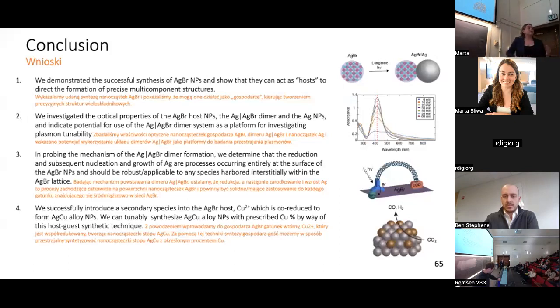So we can selectively coat those particles with a different ligand like CTAB or citrate, but there's capability for us to have simply silver nanoparticles that are ligand free. We do coat our silver copper alloys with CTAB because if we don't, they sort of crash out and aggregate in solution, which again confirms that there's likely no ligands on the surface, but that hasn't hindered our catalytic activity.